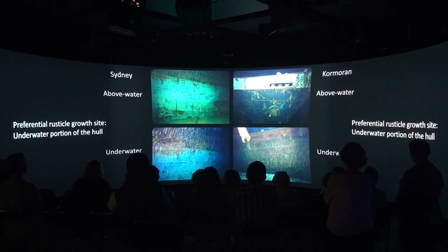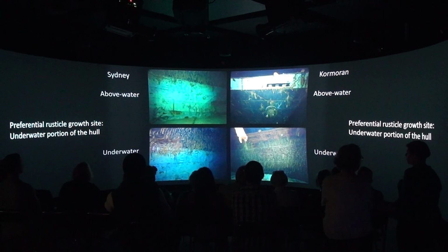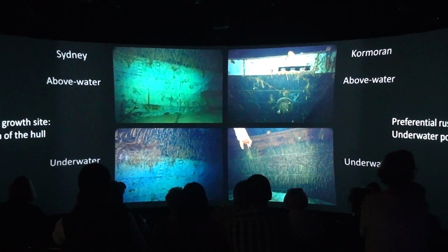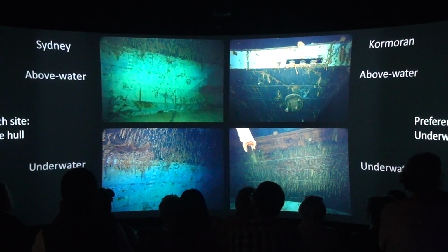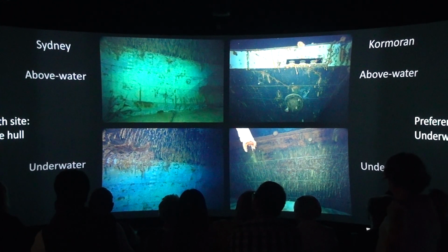So here is what I was mentioning about the above water and underwater portions of the hulls. You can see that the above water portions are basically rusticle free, and in the underwater portions of the hull, for example in the HMAS Sydney to the left, the rusticles are very localized, and in the Kormoran it's just a sheet of corrosion. And we were also thinking that it may have something to do with the biofouling present in the underwater portions of the hull. But this biofouling would mean food for deep water communities. And this is another characteristic of deep sea environments, that all the food comes from above. So when it starts sedimenting up to the bottom, the food becomes really scarce, and the only thing left is very recalcitrant organic matter.